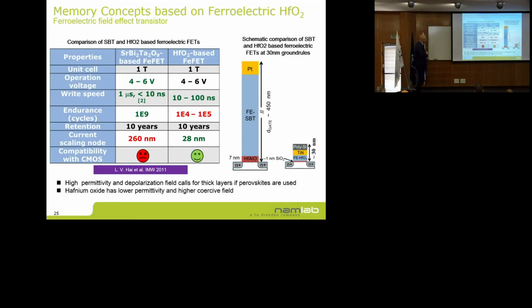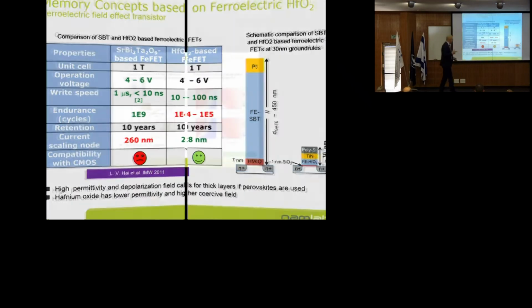Now, if you try to fix that issue, you can increase the thickness of the ferroelectric, because then the capacitance of the ferroelectric will go down. So you can do such a device, which has been shown. About 10 years ago, for the first time with SBT, non-volatile retention was shown. But obviously, this is not scalable. But if you use hafnium oxide, immediately you can do the same thing with a much thinner stack for two reasons. Coercive field is higher. Second thing, dielectric constant is lower.